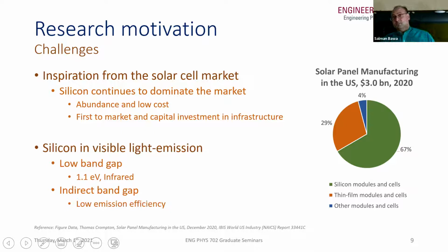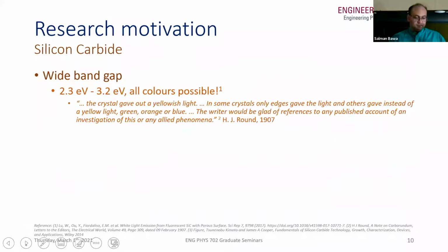Can we use silicon for visible light emission? Well, it's a low band gap element, having a band gap of about 1.1 electron volt, where most of the emission would then occur in the infrared region. And it is indirect band gap, which means that for the electrons and the holes to recombine, the efficiency is low because it's a phonon-assisted recombination mechanism.